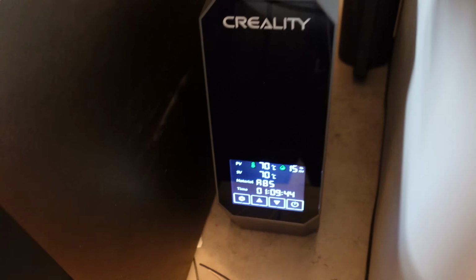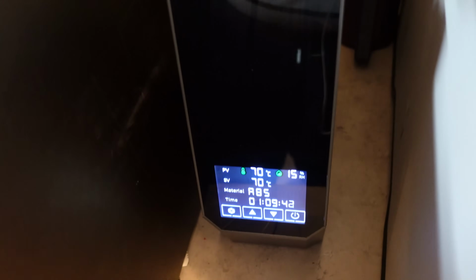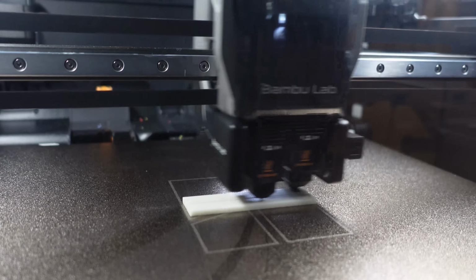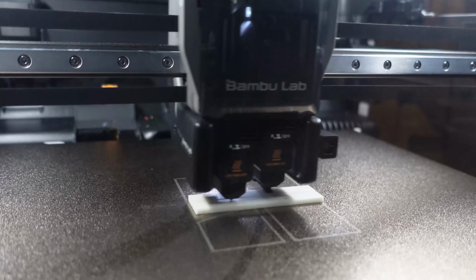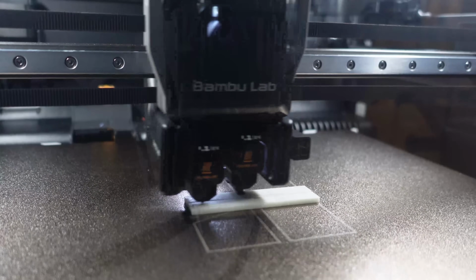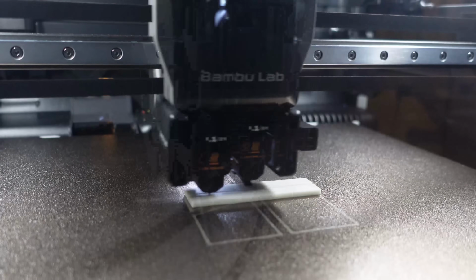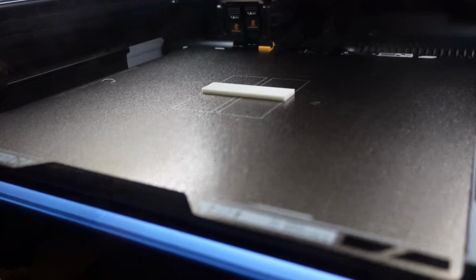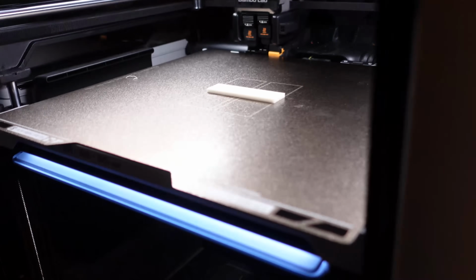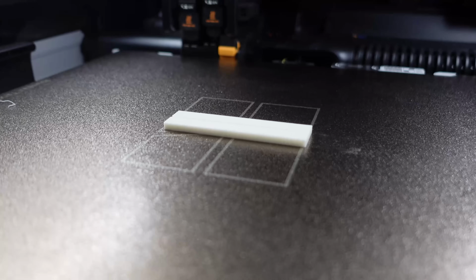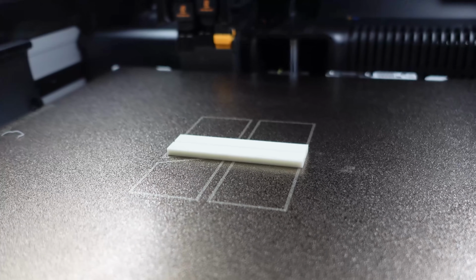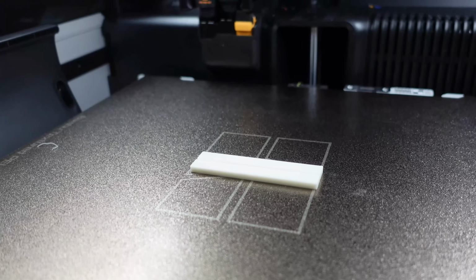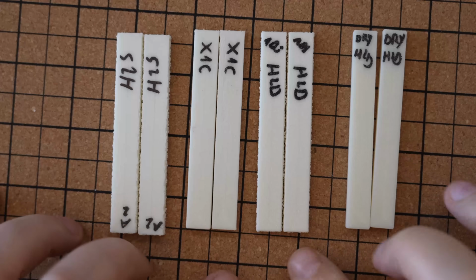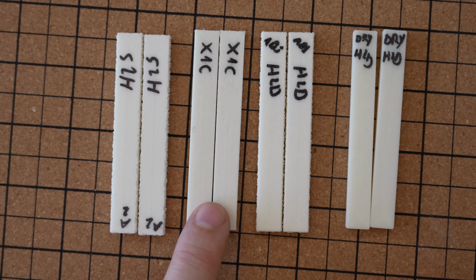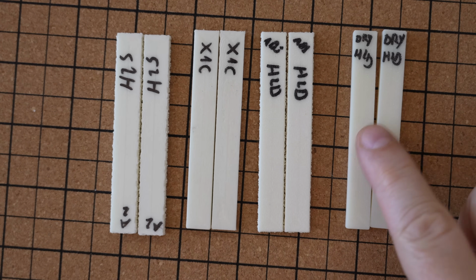Again drying the spool at 70 degrees Celsius, only 4 hours. Printing on H2D, and looks like just a minimal drying results in completely perfect printing. But why is it so much better on X1 Carbon before the drying? By the way, the smell is extremely minimal, maybe even smaller than with the PC ABS. It was printed exactly in this order: H2S, X1 Carbon, H2D, and after the drying again on H2D.